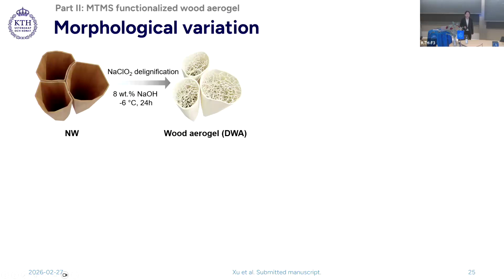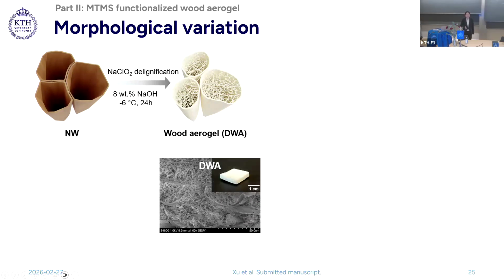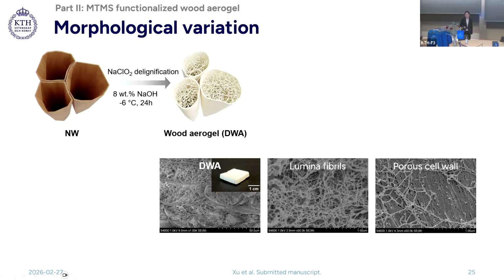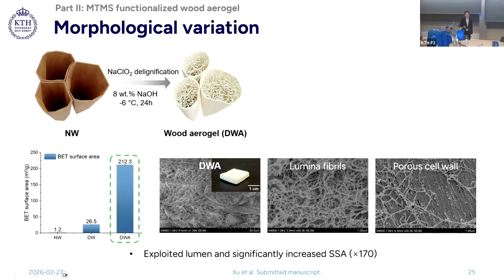The wood aerogels in this part were prepared by sodium chlorite delignification, followed by cold sodium hydroxide treatment for 24 hours. The process effectively utilizes the lumen space by filling it with microfibril networks. In addition to lumenal fibrils, the treatment also generates plenty of pores within the cell wall, leading to a highly porous structure with specific surface area up to 212 square meters per gram.